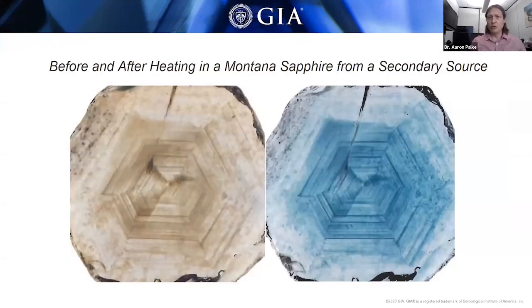Here's a little about what's going on with the heat treatment — Nathan will touch on this more in his microscopy section. On the left is a slice of a Montana sapphire polished on two sides so you can see through it. All those brown areas are little inclusions of rutile needles throughout the sapphire. When you heat treat it, you dissolve those rutile inclusions into the corundum lattice, introducing titanium atoms that form pairs with iron atoms already present. These iron-titanium pairs cause a blue color. All those blue areas in the right photograph are where the rutile has dissolved into the lattice and created rich blue color.